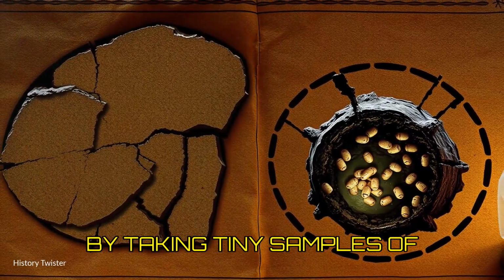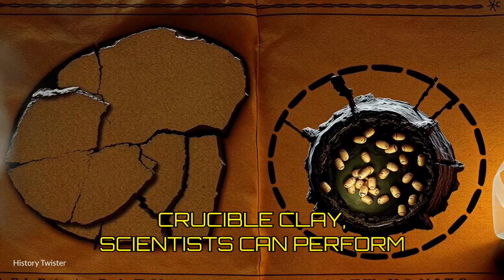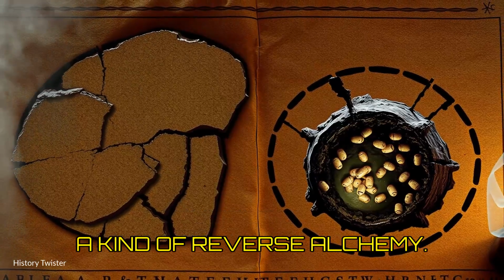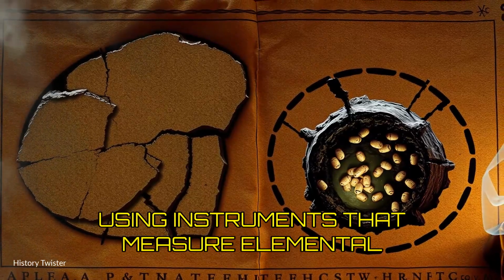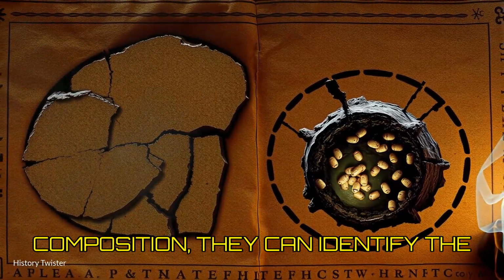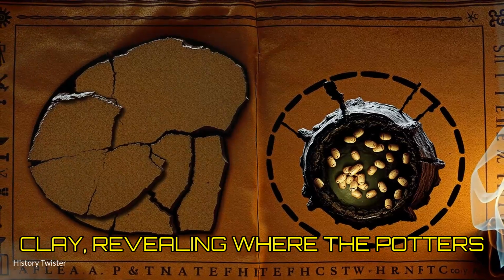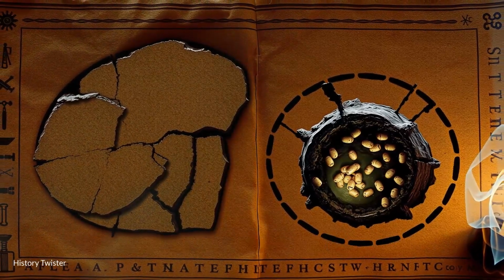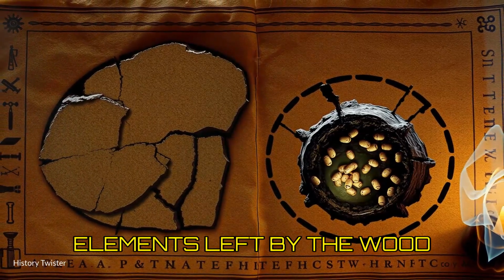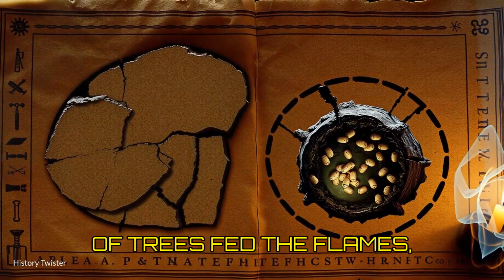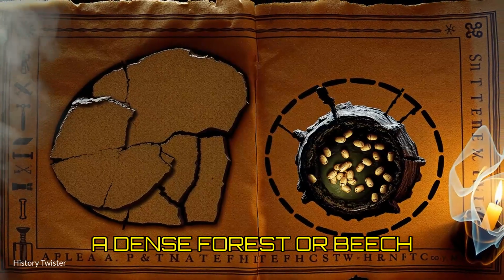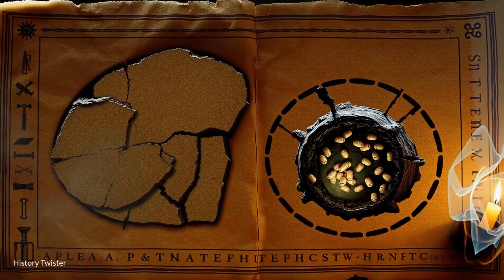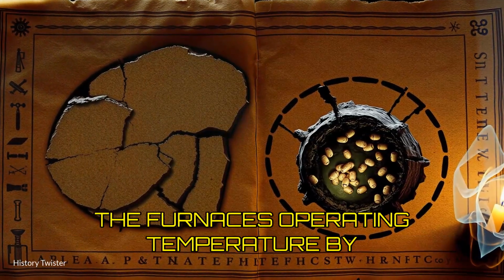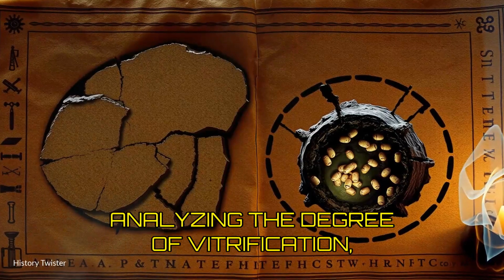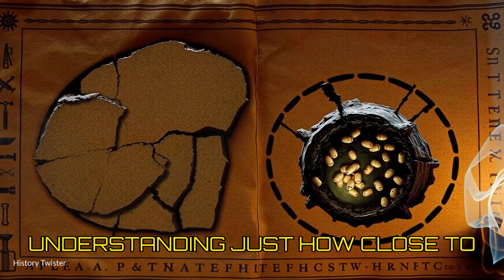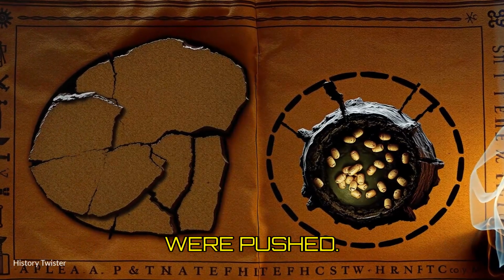By taking tiny samples of this crust and the vitrified crucible clay, scientists can perform a kind of reverse alchemy. Using instruments that measure elemental composition, they can identify the specific minerals in the original clay, revealing where the potters sourced their materials. They can detect the trace elements left by the wood ash, telling us what kind of trees fed the flames, whether it was oak from a dense forest or beech from a hillside. Most remarkably, they can estimate the furnace's operating temperature by analyzing the degree of vitrification, understanding just how close to melting point those clay walls were pushed.